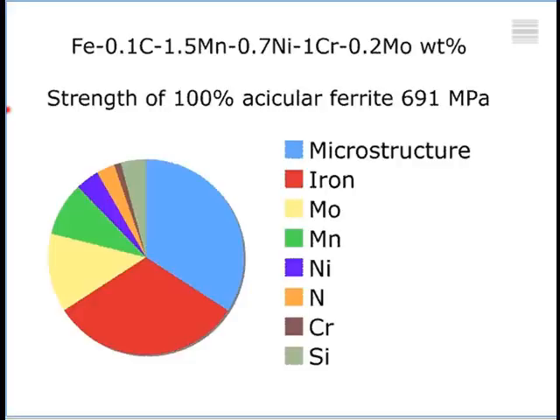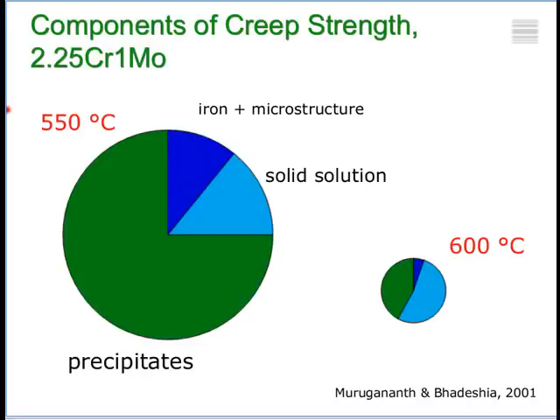Just to show you that these contributions are not constant if you change temperature, here is another set of pie charts. Here I'm looking at the strength at 550 degrees centigrade and then at 600 degrees centigrade. And the size of this pie chart is proportional to the strength. So the strength collapses as I increase in temperature from 550 degrees to 600.